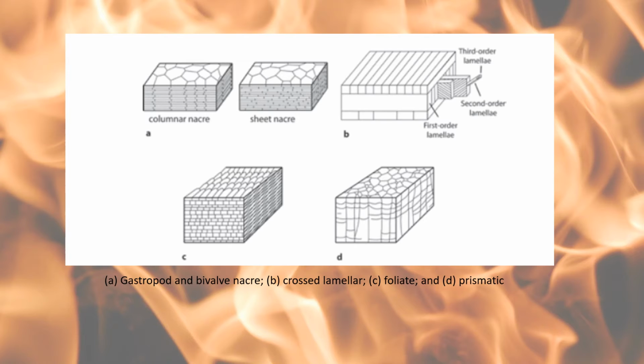C is foliate microstructure, which is particularly characteristic of oysters, as in rock oysters. These are sort of thin arrow-shaped tablets that are set like shingles, really, like roof tiles, again glued together with organics. And D is prismatic. These again are stacked tablets of either aragonite or calcite. It depends on which shell is doing the building. It never occurs by itself. It always co-occurs with another form, usually nacre. So you'll get shells that have a nacreous mother of pearl interior, and the outside, more often than not, is prismatic. It's very organic heavy, and if you whack it, it tends to come away in chunks.